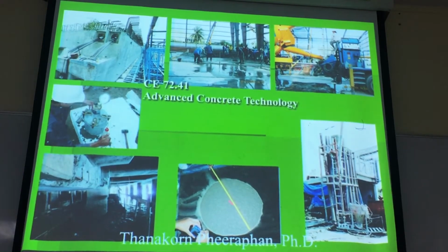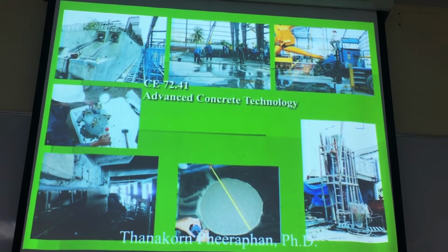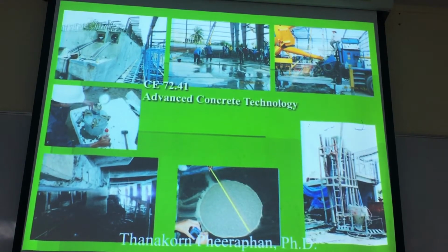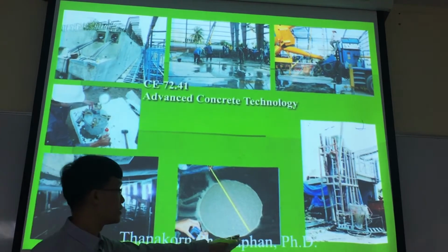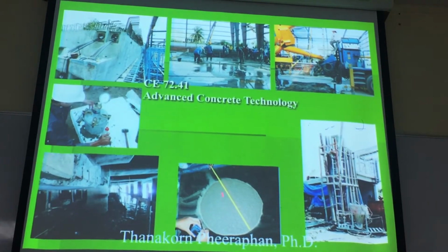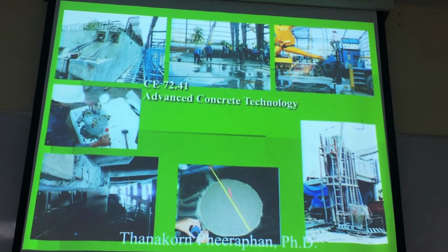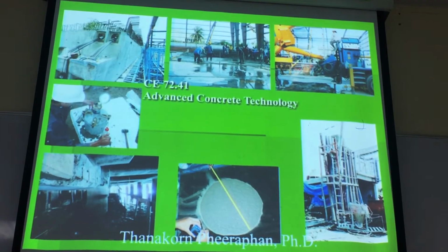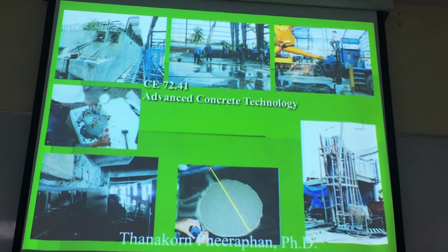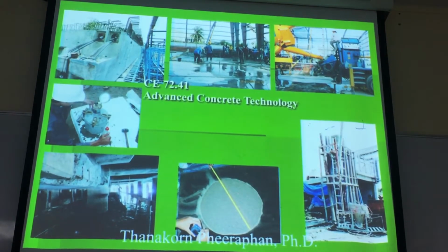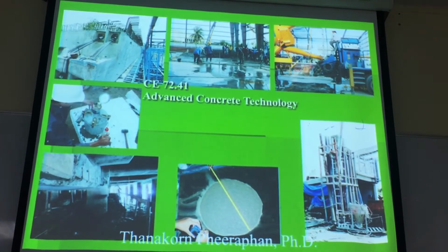We check the diameter after we use the same equipment to measure the slump, bring it up. This one will go down and then we measure the diameter. Roughly, in this number, around 80 centimeter, almost flat down. Okay, 80 centimeter. From here you can see segregation or non-segregation.